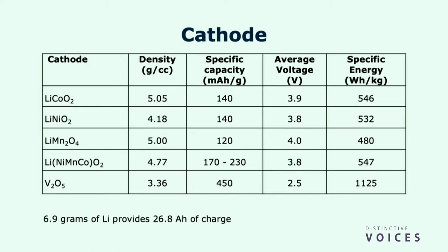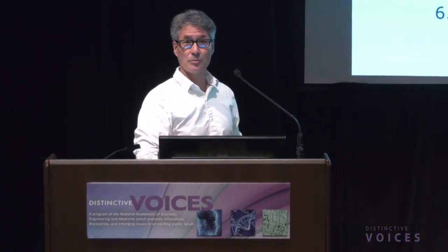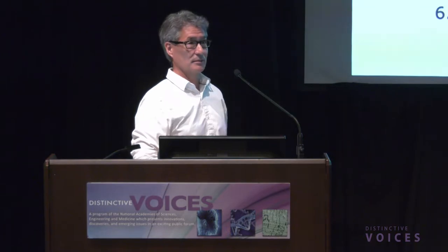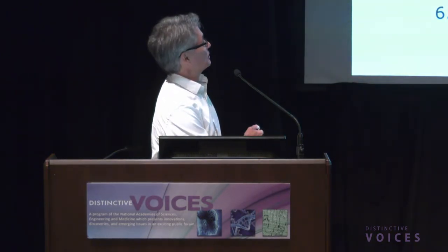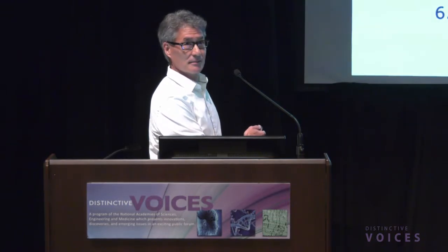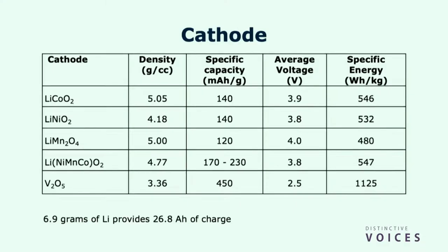This was the Nobel formulation, lithium cobalt oxide. It's still used in some cells. Lithium nickel oxide, many of us know that cobalt is problematic, the way it's mined, it's scarce, and also it's expensive. So the world does not have enough cobalt, the way it's mined is not sustainable or ethical, so we have to move away from cobalt. That's why we're looking at things like lithium nickel oxide. Lithium manganese oxide is starting to fall out of favor because it doesn't cycle well. This is turning out to be one of the winners in terms of getting rid of the cobalt, replacing that with more nickel and manganese. And that gives some of the highest capacities of 170 to 230 milliampere hours per gram.